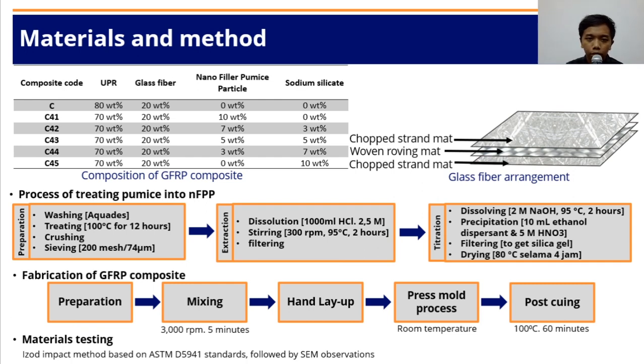In the production process of GFRP, a 3000 rpm stirring process was performed for 5 minutes to mix the matrix and filler. Then the catalyst was added just before pouring into the mold. The glass fiber types of chopped strand mat and woven roving mat are used in the arrangement as shown in the picture beside the table.